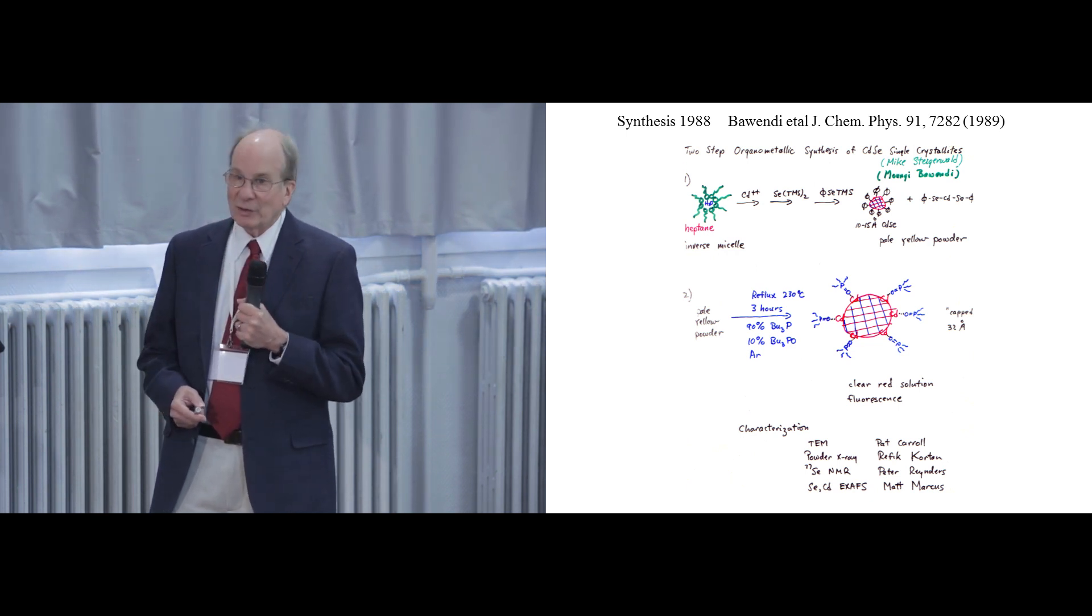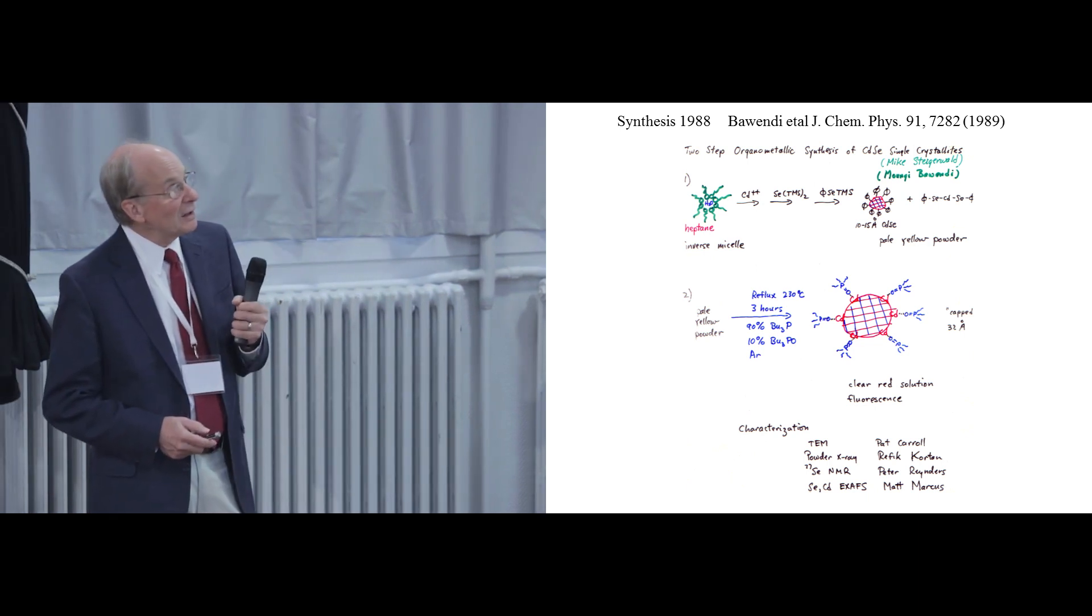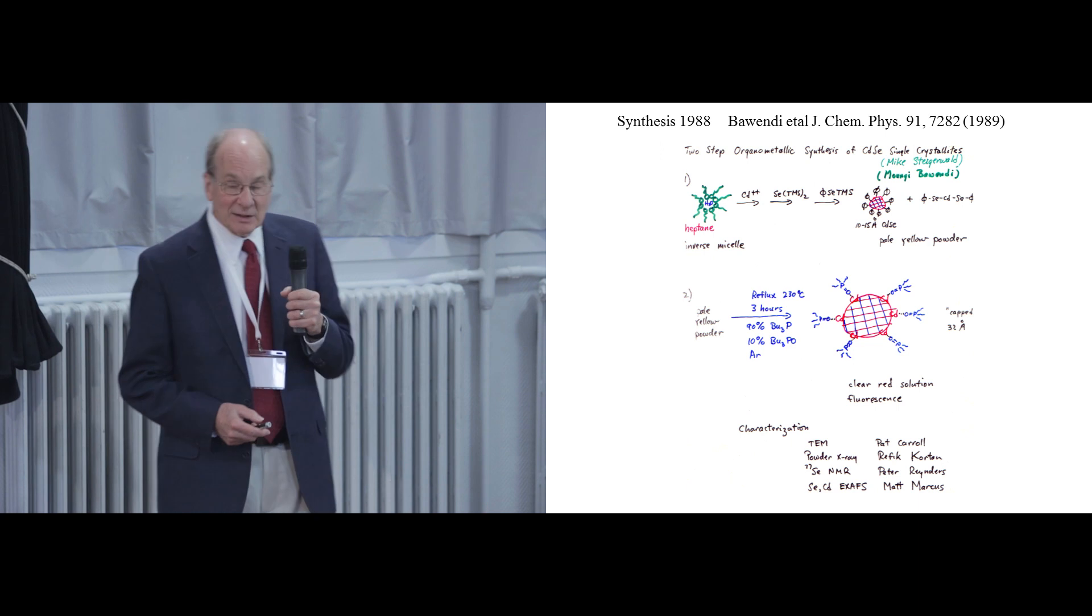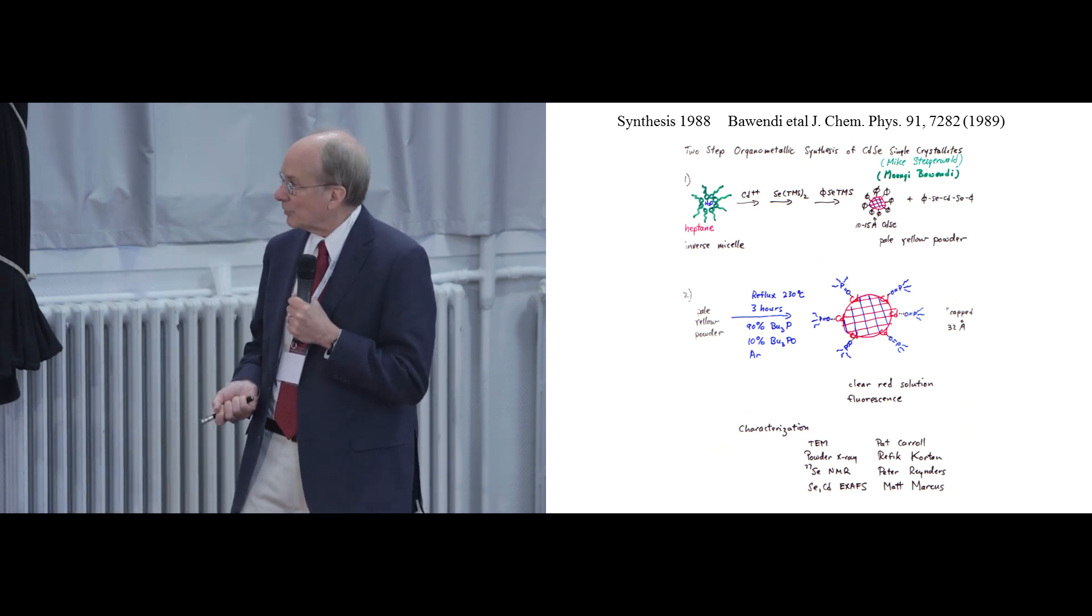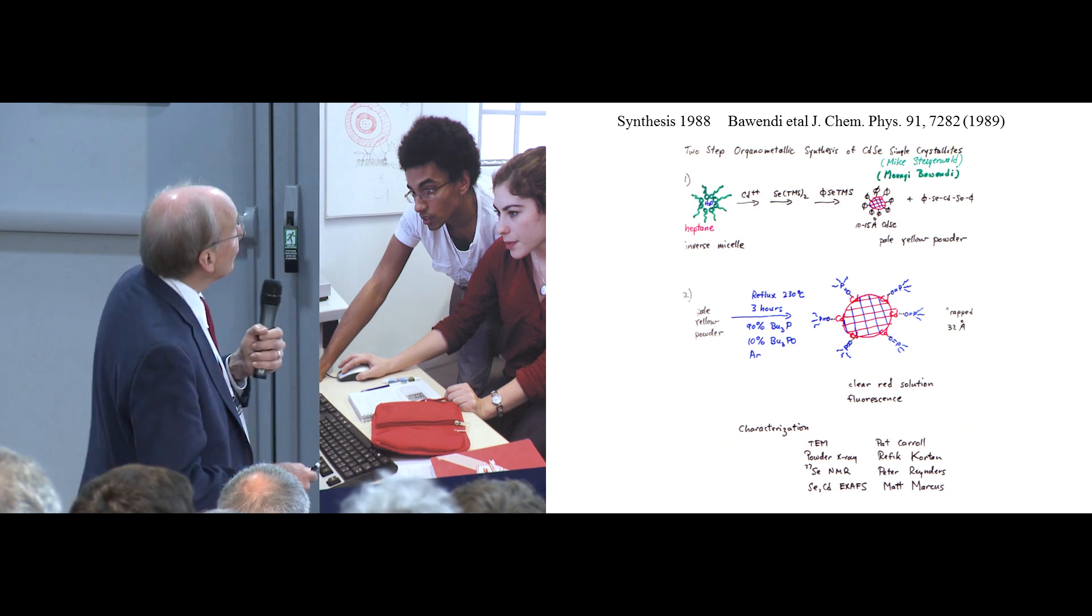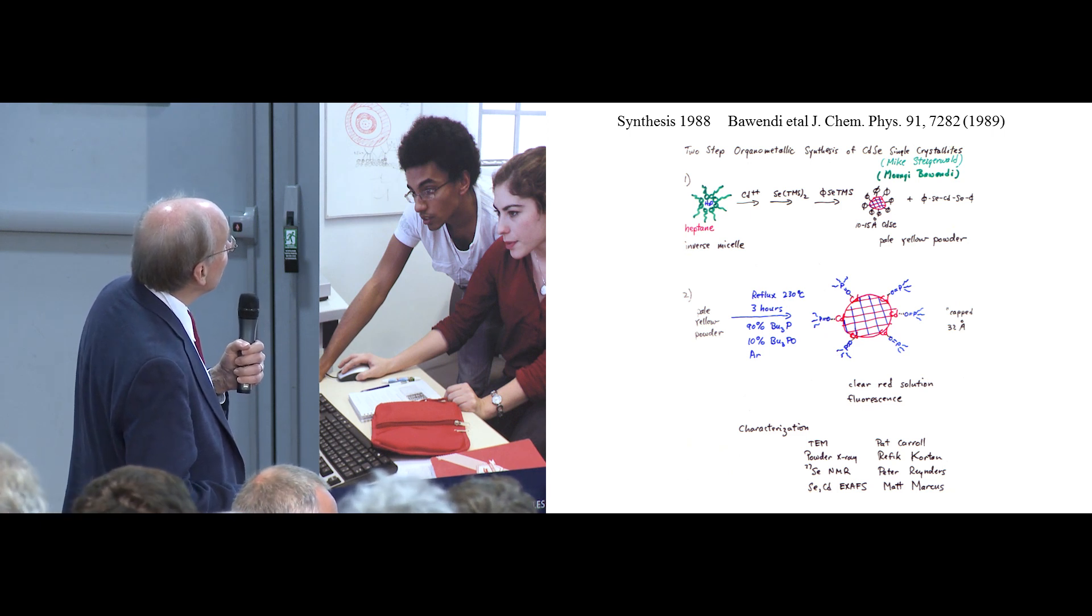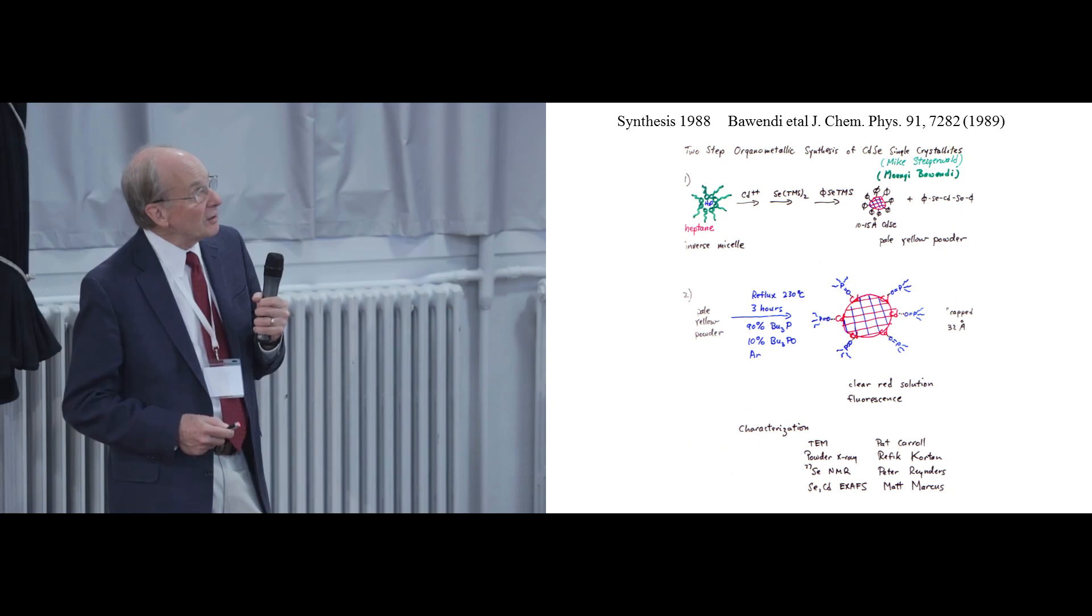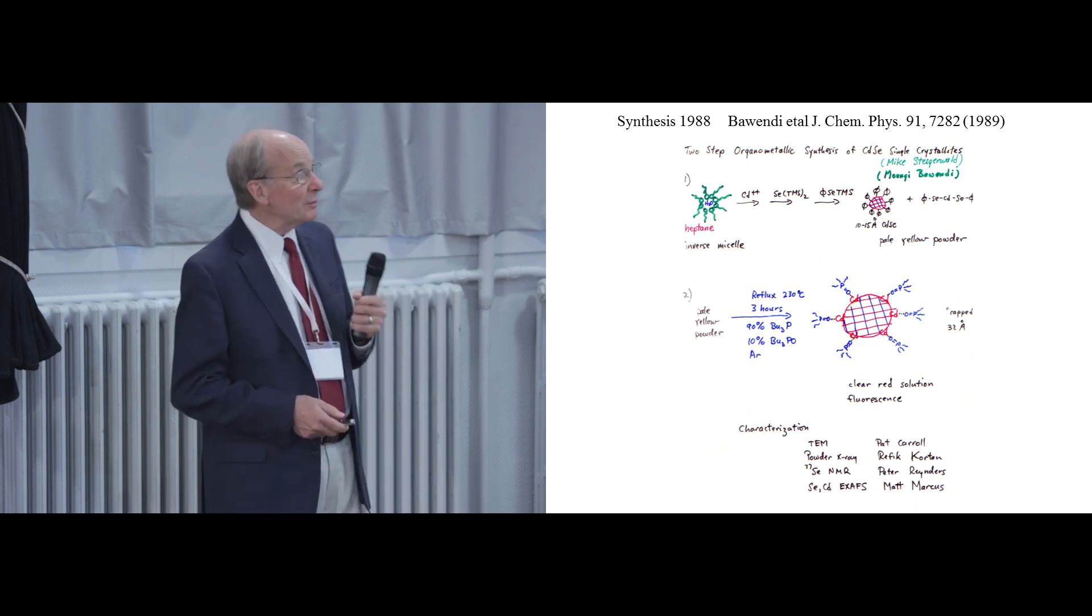They came out of solution because they were hydrophobic at this point. So they didn't like being in the water here. And the phenyl capped particles were not very soluble in heptane. Fell to the bottom. What are we going to do with it? So I think it was Mike who decided the phenyl groups cap the selenium. In principle, the cadmium is bare on the surface.